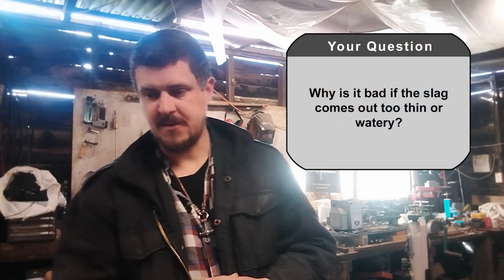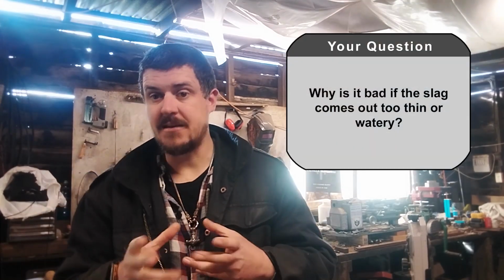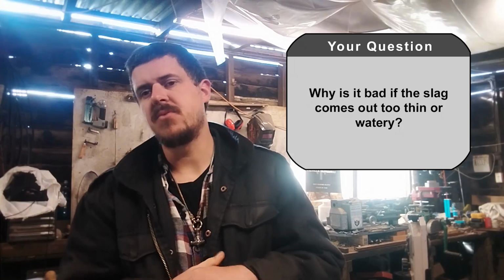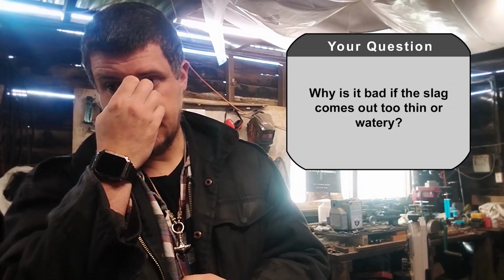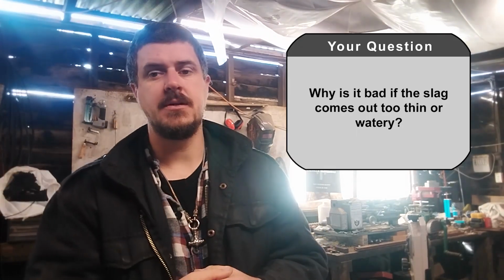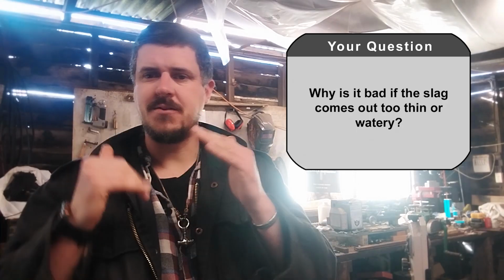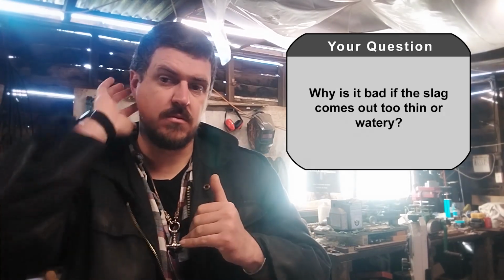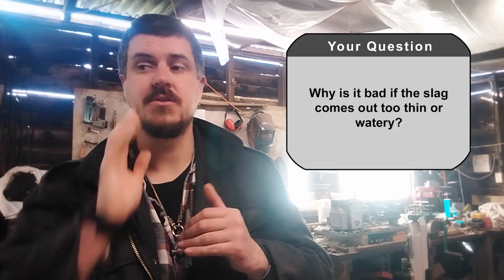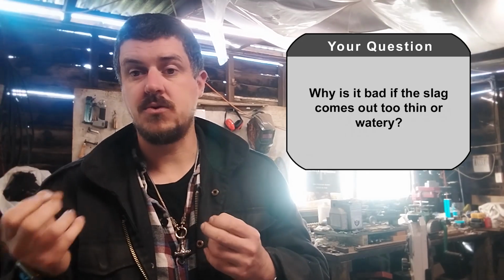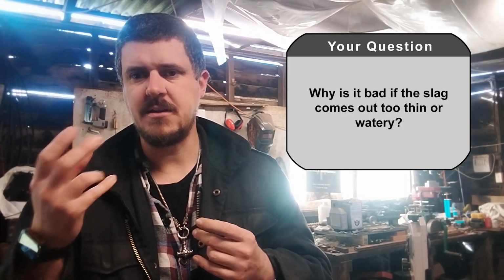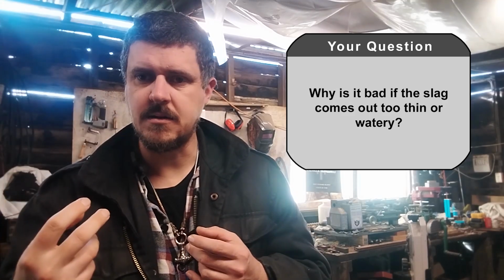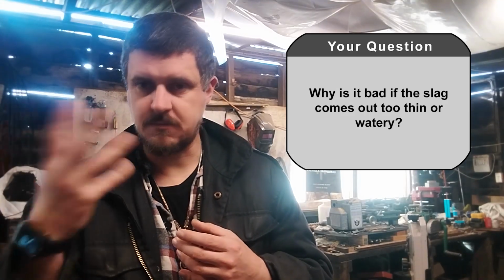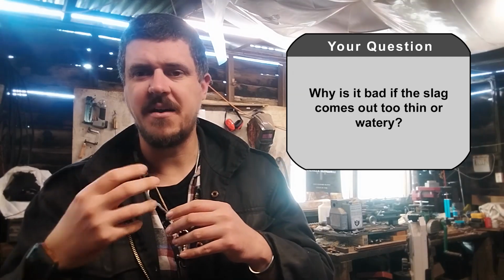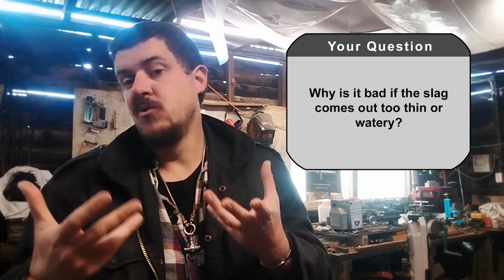The next question is, why is it bad if my slag is too thin? And so if the slag's too thin and runny and watery when it comes out, it probably means too much flux, or possibly too high a temperature. So it's finding a balance of those two things which will lead to good slag formation. So if it's too runny, the thinness of it means it will be carrying away iron from the sintering conglomeration of iron that's in there, and if it's pulling away iron, you're losing iron.